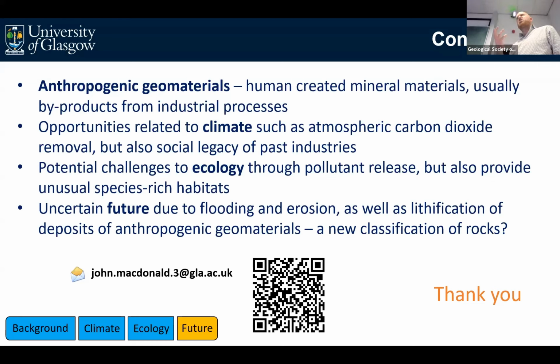It's sort of armoring it and stopping nasty things getting out, toxic metals. But if you were to then disturb that, either mechanically, grinding it up, or it gets mucked up on a beach by the tide, by the waves, or if you had some quite extreme chemical change that caused the calcite to dissolve, then you come out of that, I don't know, almost like a metastable state. It's achieved some kind of stability, but that could be changed.